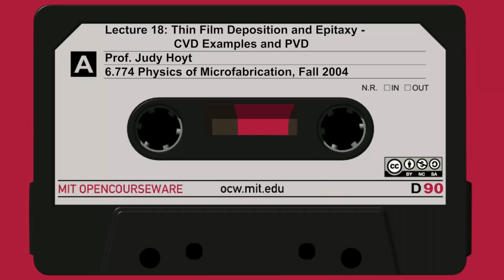Typical pressure for poly deposition is about 200 millitorr, maybe up to a torr. A torr is a little bit high. The low pressure here, in the hundreds of millitorr range, improves the film thickness uniformity. And again, the temperature range is pretty tight: 575 to 650. An important number to keep in your head, an important temperature for polysilicon, is 580.